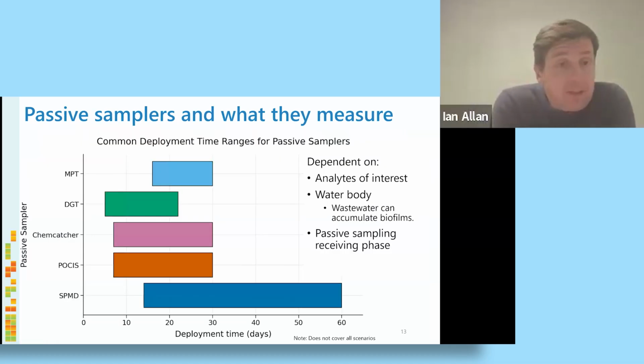On this slide, you can see the typical deployment times for the different samplers. For the MPT, which has been used a lot for PFAS, DGT, ChemCatcher, and POCIS, the deployment times are usually no more than about a month. In the case of DGT, for example, when using agarose gel, the gel will tend to not last much more than this kind of time. Samplers like SPMD, silicone, and LDPE can be left a lot longer to sample, and we've had deployments up to about 2 years at deep water sites in the marine environment.